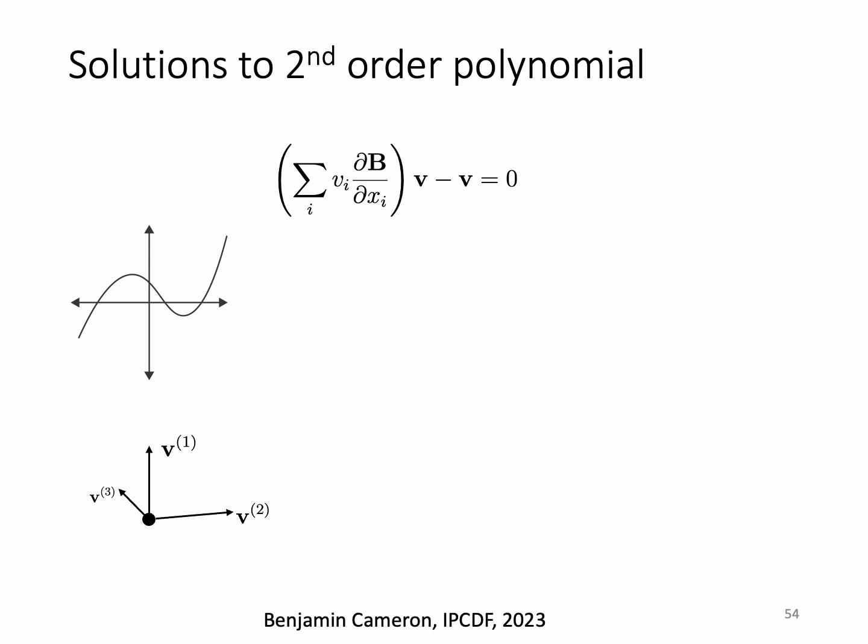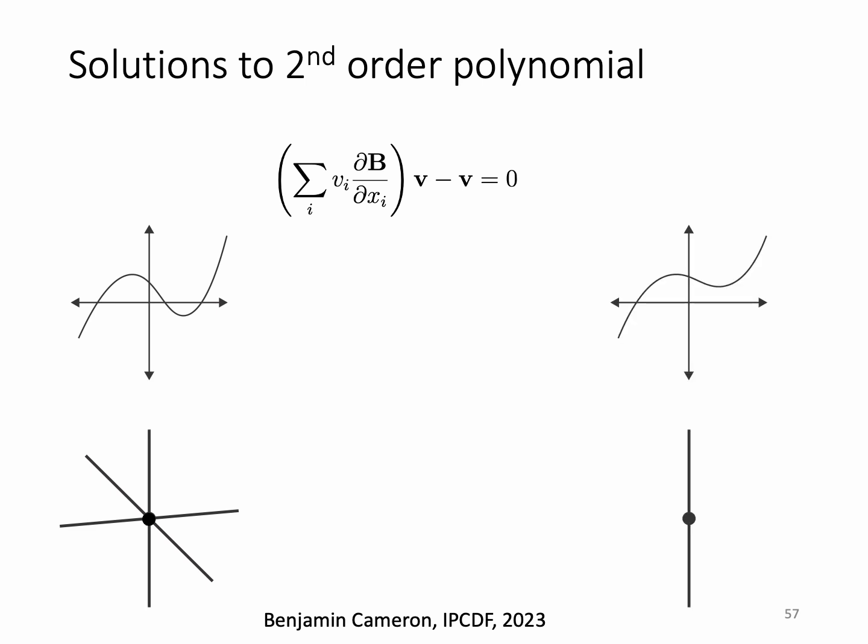Each one of these v's, if we traverse a distance out, there will be eigenvectors and characteristic lines given by these crosses. But again, it doesn't matter what the magnitude of v is. So we're going to have all these crosses passing through the singularity like this, and these connect up to form characteristic lines which pass through the singularity. So in the case of 3 solutions, we get this structure of 3 characteristic lines passing through the singularity. There will always be at least one solution, because the cubic has to intersect at one point.